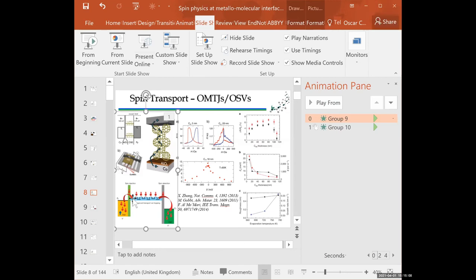Yeah, actually I worked on magnetic tunnel junctions based on MgO, where we consider there are a lot of defects that create a lot of localized states, and then there is hopping. So hopping is a negative in those tunnel junctions. But here you're telling me that if there is hopping, it flips the spin, so there is a certain thickness where there is more spin flipping. Isn't that so? With each hop, it is losing spin, right? It is flipping the spin, right?